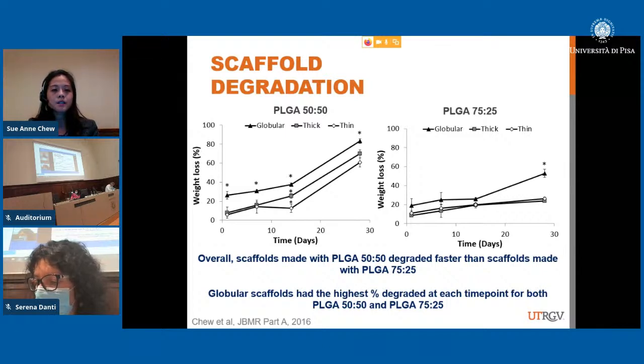We saw that the globular was the one that actually was losing more of its weight over time, and we looked into it more, and we saw that this occurs because when you have the globular scaffold, you have your acidic byproducts that are stuck in the scaffold, right? That lactic acid, the glycolic acid. So that instead will auto-catalyze the degradation of the other ester subunits. So that's what we were seeing. The entrapment of those acidic byproducts led to that. So that's why we're seeing this opposite effect.